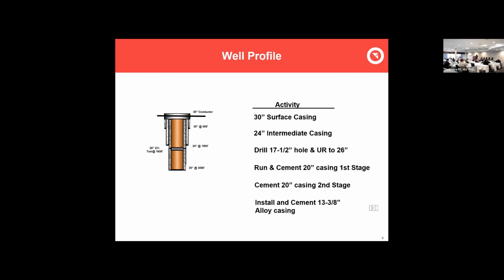And our alloy string, some of those alloys are as much as $3,000 a foot. So I think we are extremely cautious anytime we cement any of those, regardless of what practice we use. And in this case, we actually do a full casing to casing cement job. No outside risk of any formation. So we make sure we cement that string in pure casing to casing. And then we complete the well, typically 12-inch open hole, 12¼ inch.